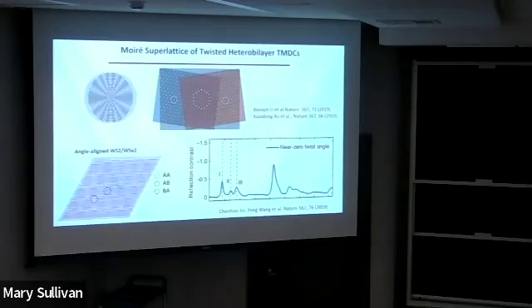And this gives you reduced kinetic energy. So potentially that's a nice platform to form strong correlation, because kinetically it's reduced and also it's 2D, so Coulomb interaction is intrinsically very strong. Right? So previously, Feng Wang at Berkeley showed that in the WSe2 and WS2 layers, instead of twisting, they tried to intentionally align them at either 0 degrees or 60 degrees. Because the lattice mismatch is roughly 4%, you have a moiré superlattice of roughly 8 nanometers.